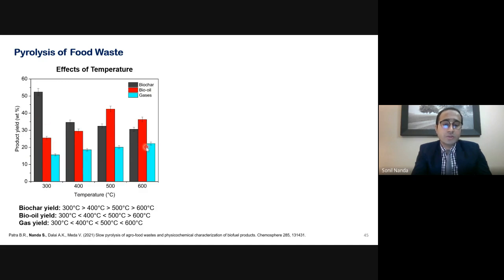So the biochar is shown in gray color here. You can see the yield of biochar decreasing as we increase the temperature. The bio oil, shown in red, shows a high yield at 500 degrees Celsius, after which it tends to decrease at 600 degrees Celsius. And the gas yields tend to increase constantly as we increase the temperature.